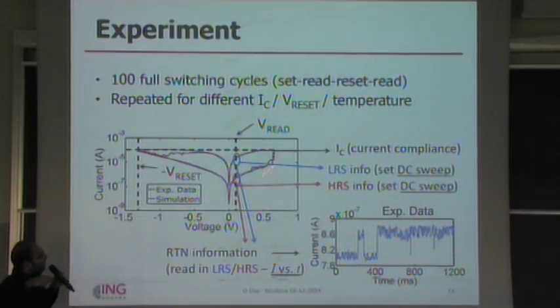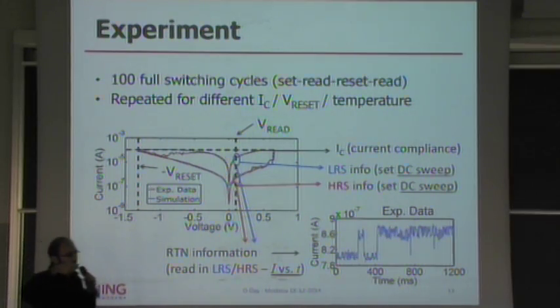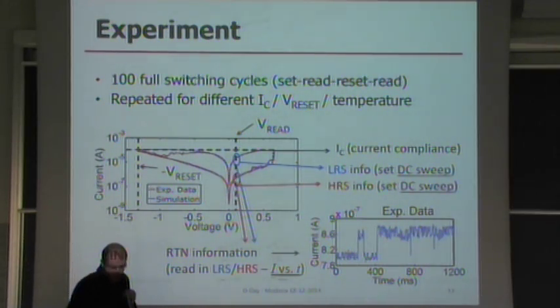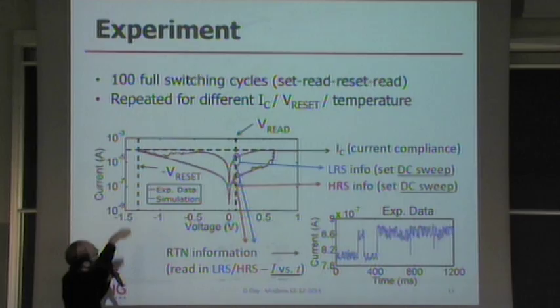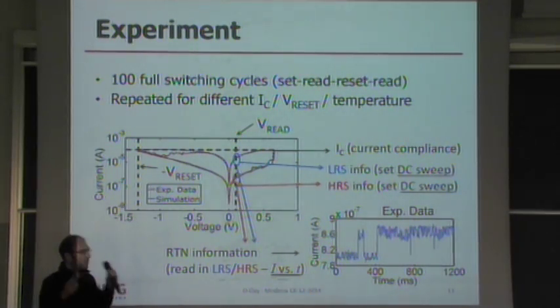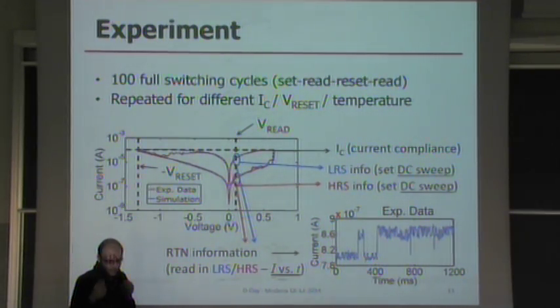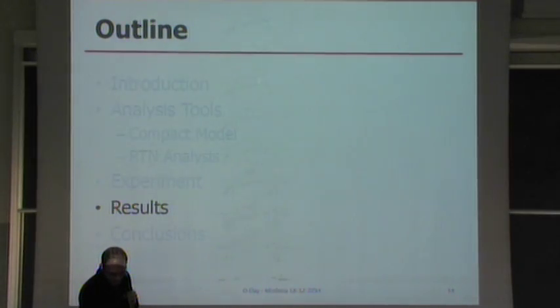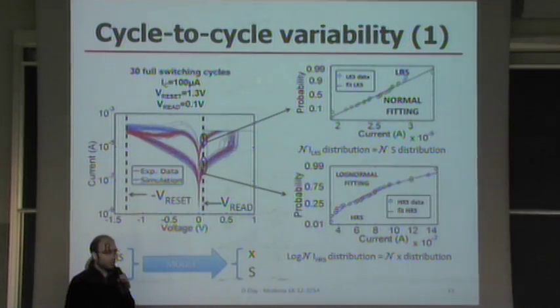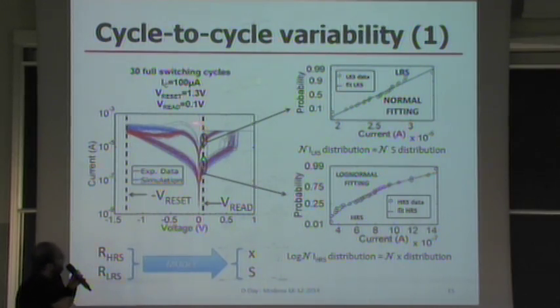So we have IV information for both processes, and then we also have I versus T, potentially RTN information in both resistive states, 100 cycles. And of course, we can repeat this for different current compliance, different devices, different reset condition, different whatever. And first of all, we tried to devise a model for the cycling variability. This is a cycling variability. This is just switching the device in the same condition.